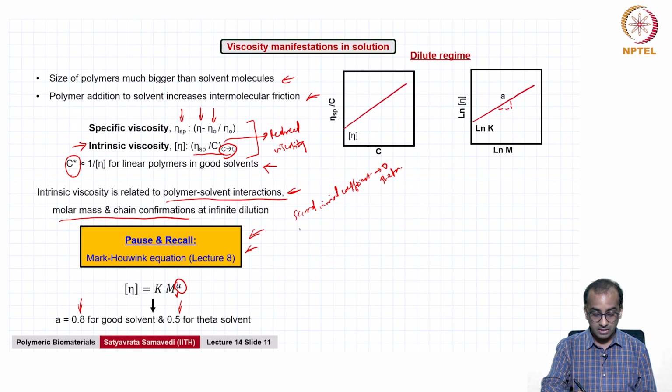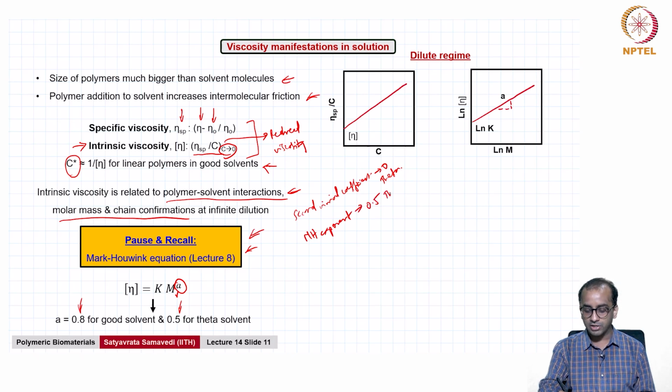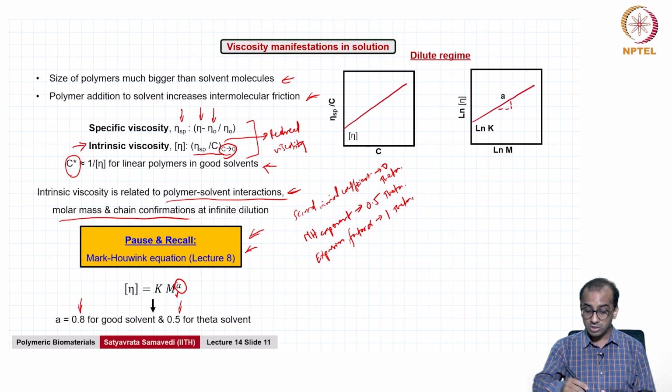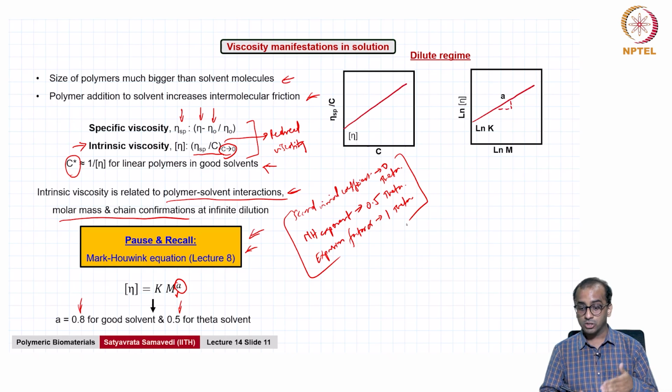We are now looking at the Mark-Houwink exponent, which is 0.5 for a theta condition, and we have also looked at the expansion factor alpha, which is 1 for the theta condition, because it's simply the mean square distance in the solvent to mean square distance in the theta solvent. When the solvent happens to be the theta solvent, you get 1 for this. So, this would be a good thing for you to keep in mind and remember as ways to understand solvent